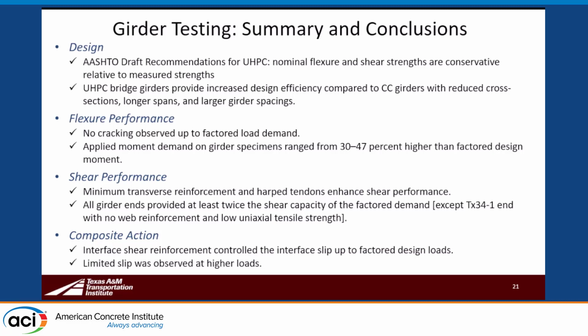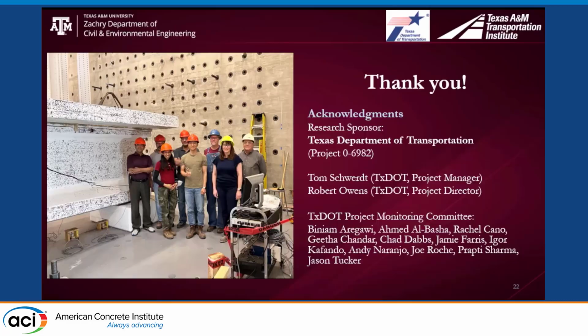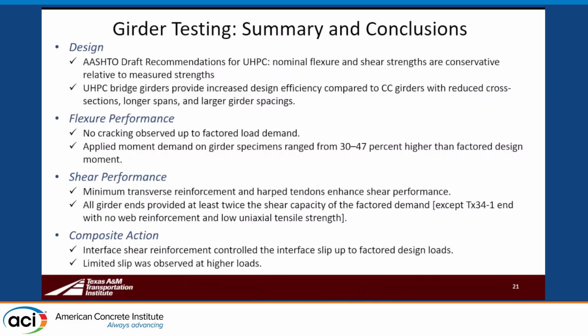In terms of the structural performance, flexural performance was quite good. We did not see cracking up to factored demand. And then we also were able to get some additional reserve capacity. Shear performance was also, I think, quite good. It was interesting to finally get a chance to check this in full scale at the end of this project. And finally, our composite action worked well in terms of the interface steel that we provided there. We saw just a little bit of slip that happened after factored loading, but that was, I think, just a little bit of the release at the interface rather than any kind of structural problem.